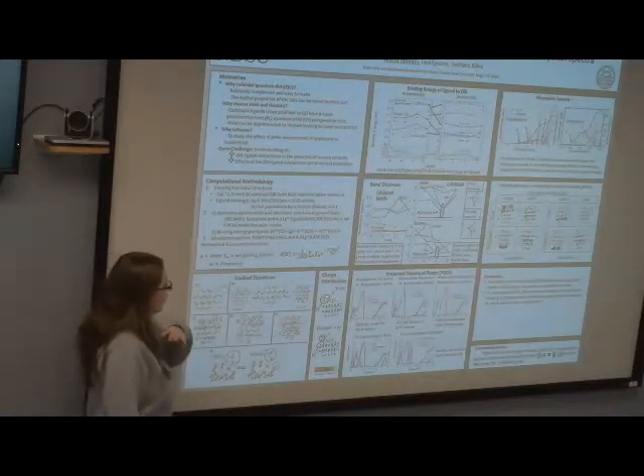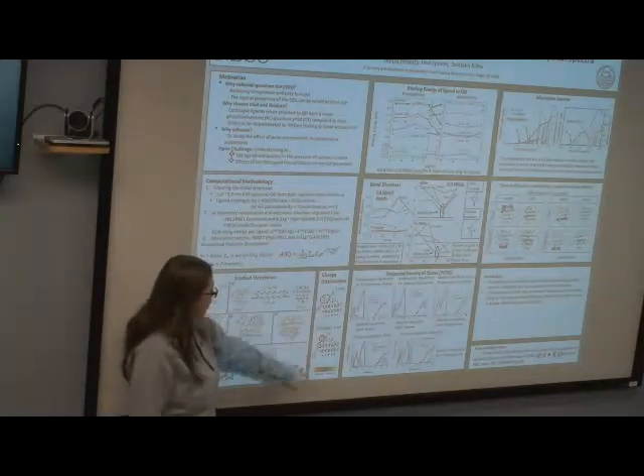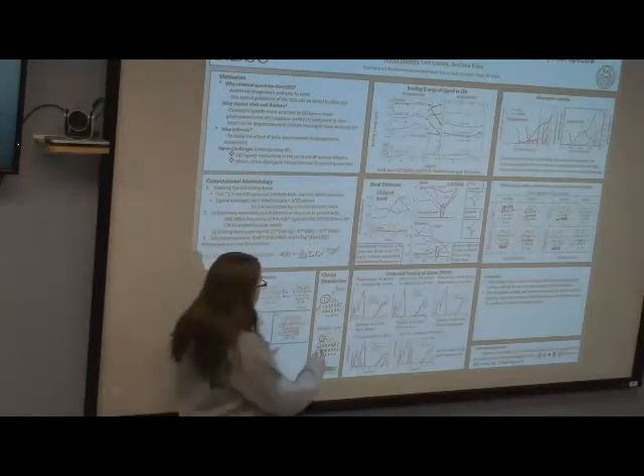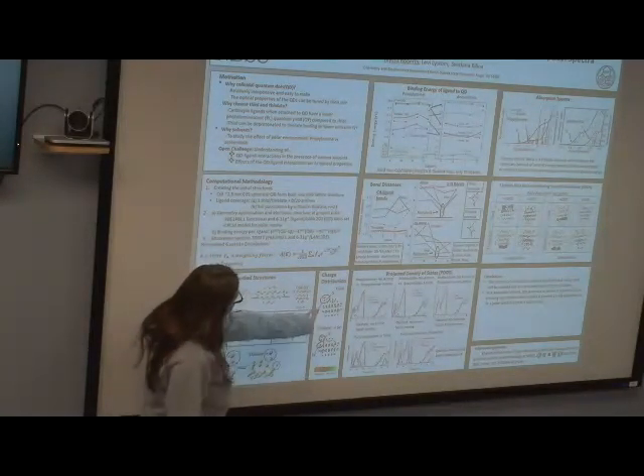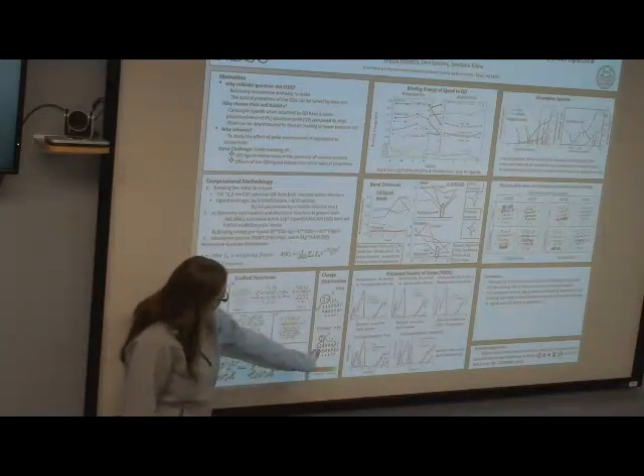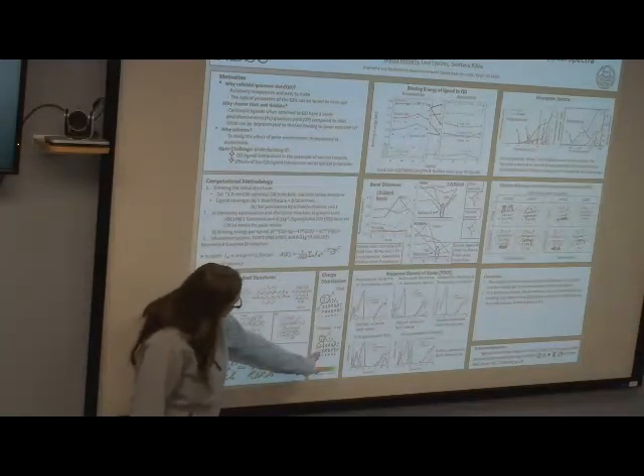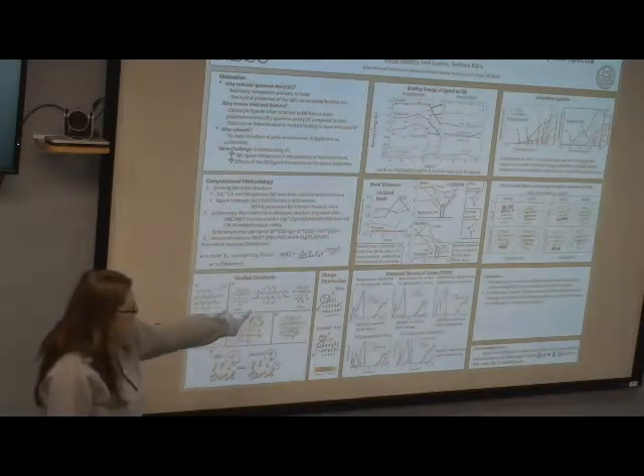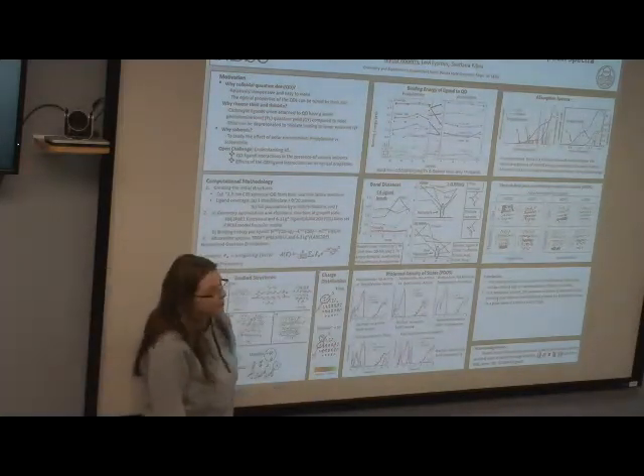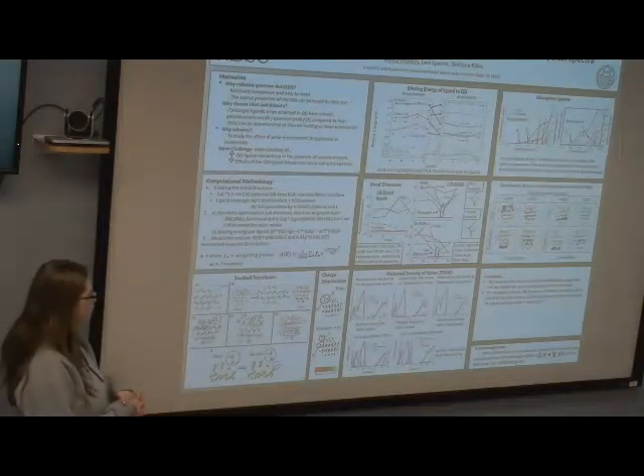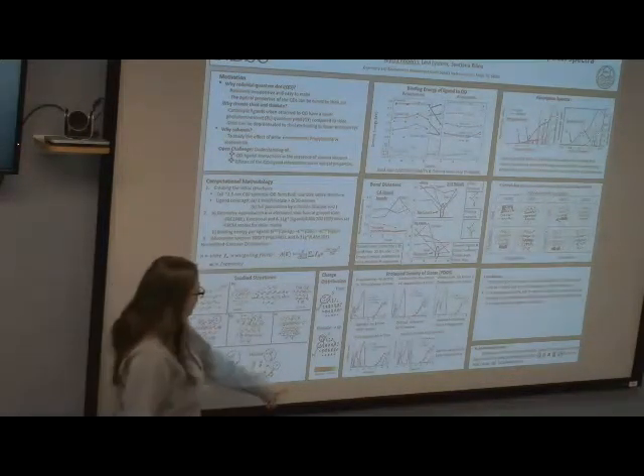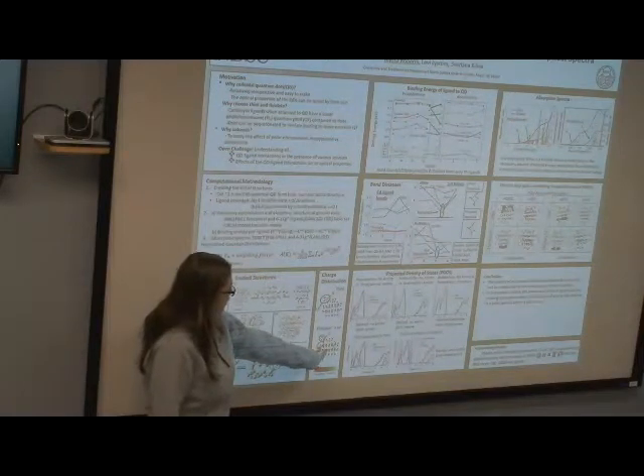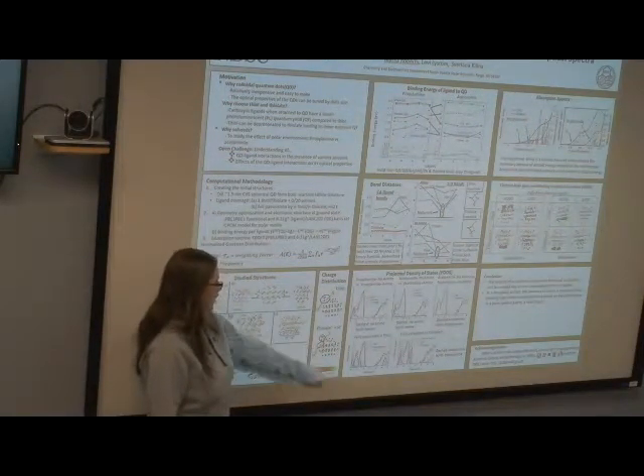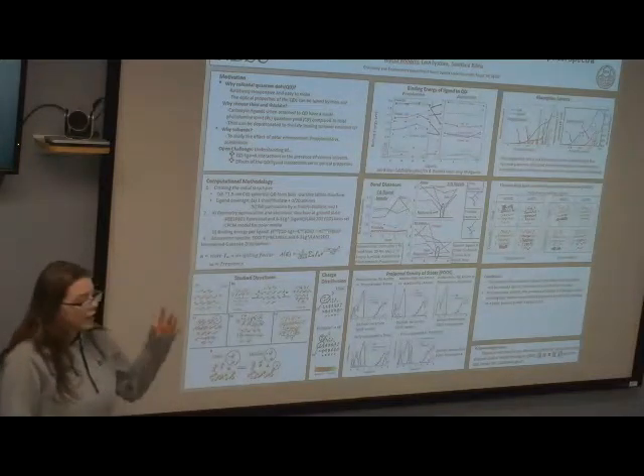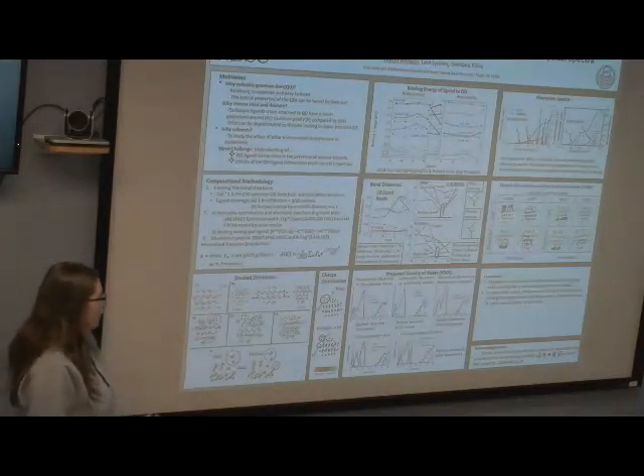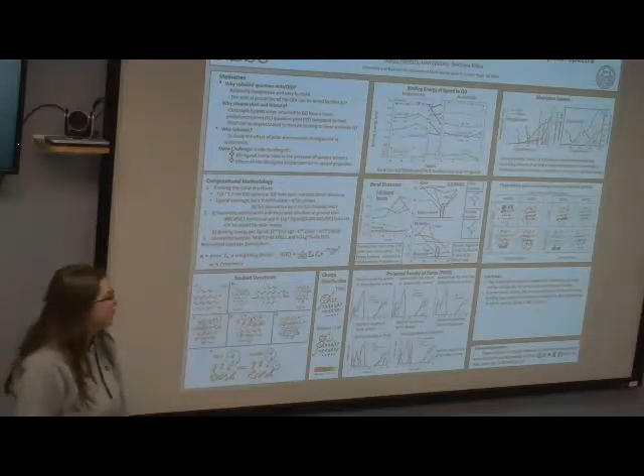Anyways, focusing on the transition between thiol and thiolate, on your thing you can probably see, but up here it's kind of hard to point out, this sulfur is less electronegative than this sulfur down here, and that can be seen here and here. So the proton is pulled to the surface sulfur because it is more electronegative and is more stable that way. And even after the proton moves, the surface sulfur is still more electronegative than the sulfur in the thiolate, so it stays there, relatively speaking.